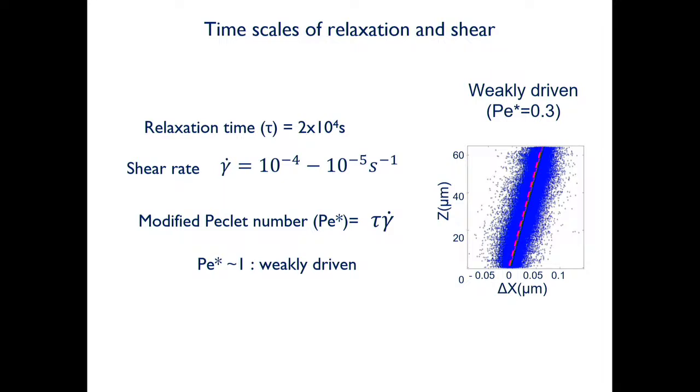that we are working at, what is being plotted here is the displacement of the particles. This is the kind of geometry that we have: one of the plates is being moved and the other plate is stationary. This is a plane shear, and if you look at the displacements of the particles as a function of distance between the boundaries, you see that there is a linear displacement profile. There are no shear bands in the system, it's a homogeneous flow.